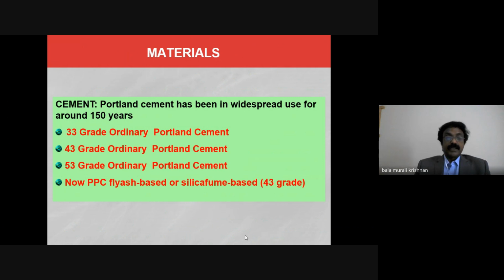Earlier in India we were using 53 grade cement, but some curing issues were coming because of early strength. 53 means 53 Newton per millimeter square, the compressive strength of cement in terms of mortar. That's why right now we are mainly focusing on the durability aspect, not just the strength point of view. Strength and durability, two things are very important. During the serviceable time, you should not get any crack or expansion or temperature shrinkage or thermal variations. You should avoid these during its serviceability condition. That's why in our Indian scenario, people are worried about the durability aspect. That's why right now people are using PPC, either fly ash based or silica fume based.